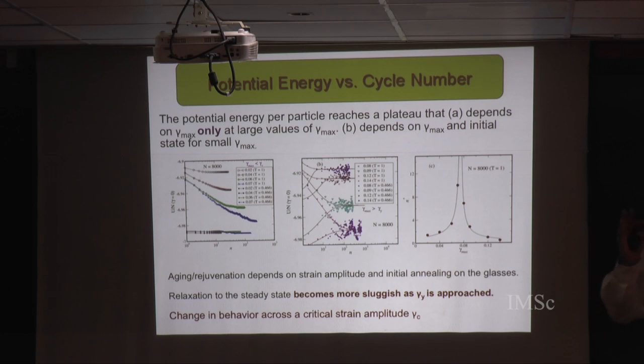So for this set of amplitudes of strain, the behavior is qualitatively different from the previous set, in the sense that the system seems to forget about its initial conditions and reach a common state as you apply many cycles of strain.